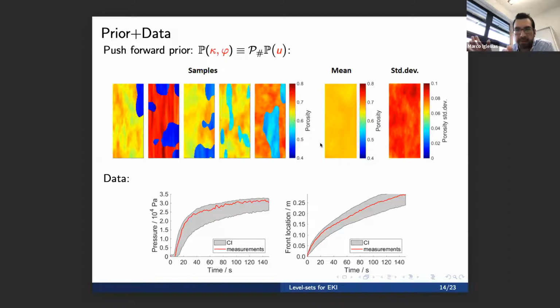So we have 400 samples from this push-forward prior that you can see here, with some mean and some standard deviation, for which we have selected a threshold for the LevelSet function. Here, the LevelSet function will give me the defective and non-defective regions, as you remember. So we have played with the hyperparameters to allow for various sorts of variability. Some defects will have elongated features because they have longer correlation length along the vertical direction, and some the other way around. We have played with it so that all the particles are prevented from the situation of the collapse and so on. And the threshold is high to ensure that under the prior there is no knowledge of where the defect is.